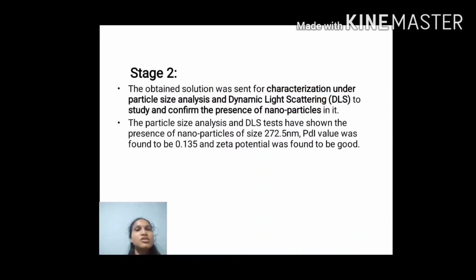Stage 2. The obtained solution was sent for characterization under particle size analysis and DLS to study and confirm the presence of nanoparticle in it. The particle size analysis has given the result: 0.135 value of PDI, and zeta potential was found to be good for the boiled solution.